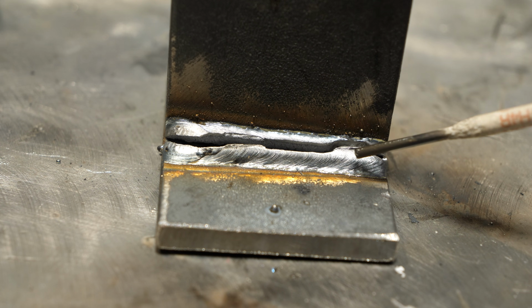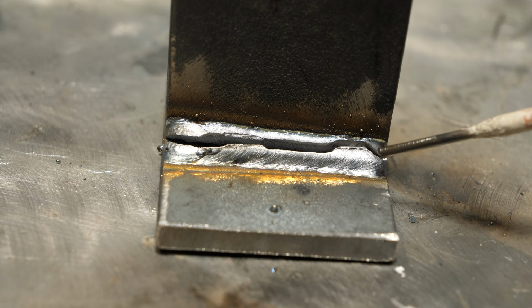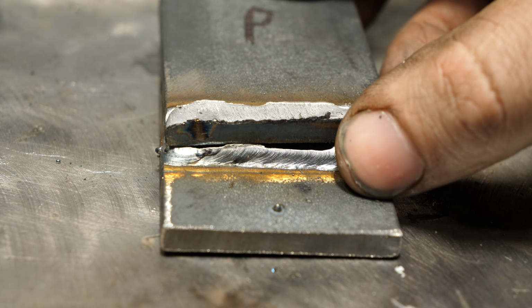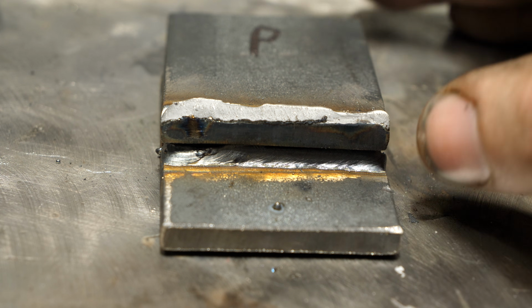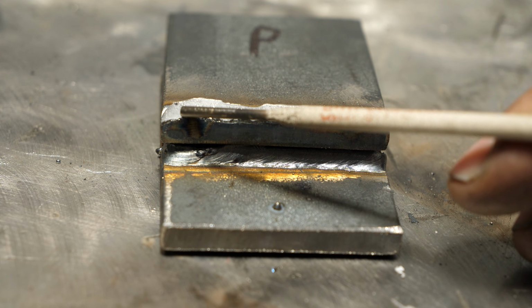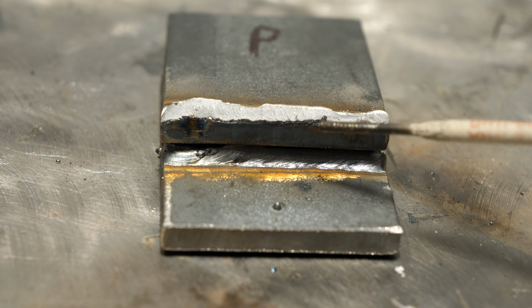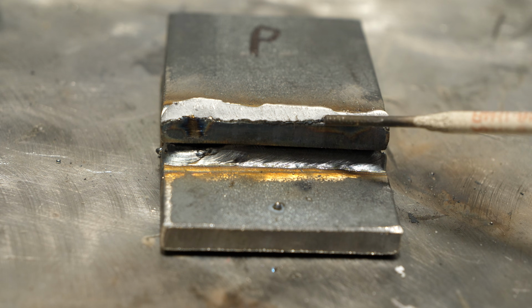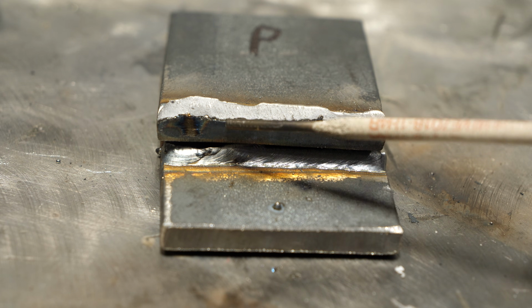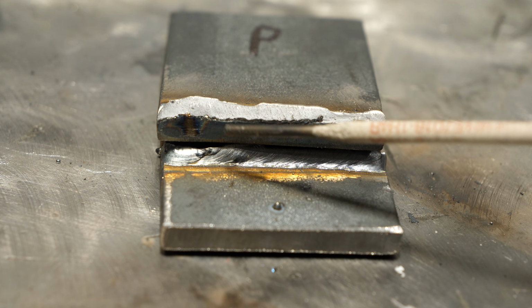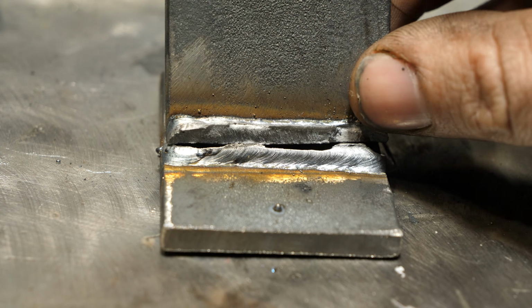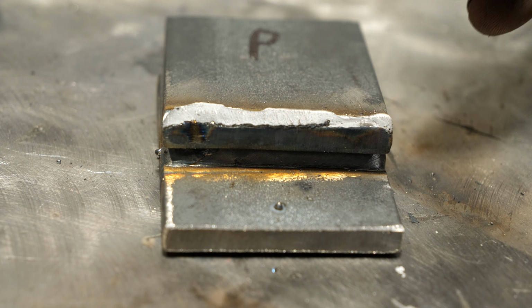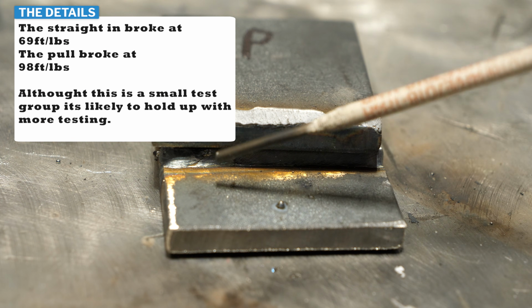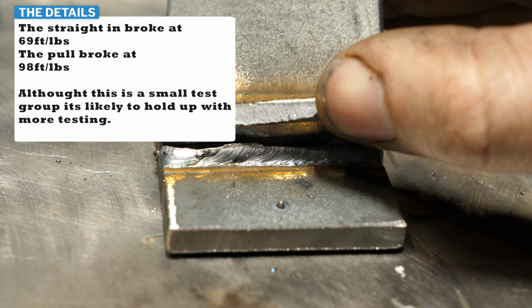So part of the reason why the push broke at a lower result than the pull is due to this little bit of lack of fusion at the start. However, when we look at the internals of it, this doesn't look that bad. We have some breakdown of the plate here. We have a little bit at the start, and it's hard to see because of all the crap that's in here from when it broke. But for the most part, the original edge is not broken down at all. There's really very little to no root fusion, but I would say it's a little bit more than the straight-in angle. And simply because of the better sidewall fusion this had and a little bit more root fusion at points gave this that much more strength over the straight-in.